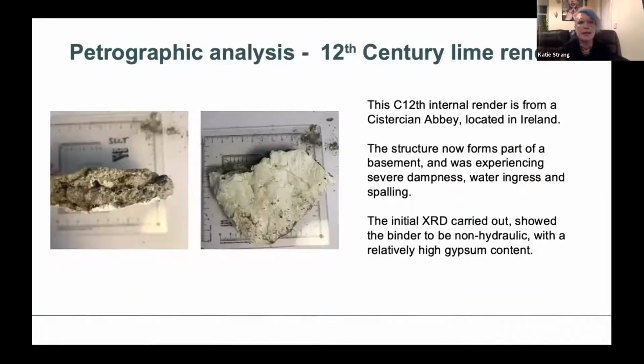I'm going to start with an example which is of a 12th century lime render, and this was discovered in a Cistercian abbey located in Ireland. The structure was actually part of a basement of a shop, so they were very unaware that this actually existed up until quite recently. And obviously, with it being in a basement, there were a lot of issues with damp, but in particular, the lime render on the walls was going through a lot of spalling, and there were big, huge chunks coming off. You can see on the surface here that it's got a layer of paint. This is actually lime wash on the surface.